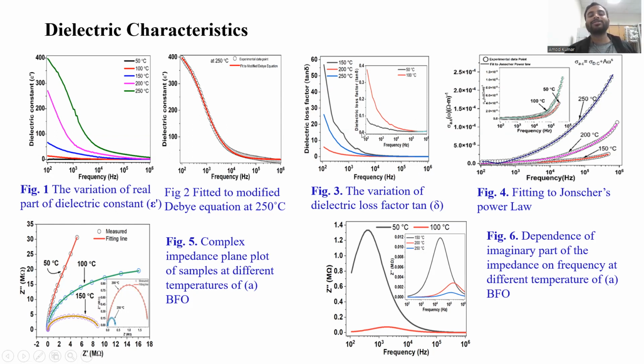So there is the dielectric loss factor. As in the previous one, with increasing temperature the dielectric loss increases, and with frequency the dielectric loss decreases. One important thing is that the development of defect-induced dipoles due to localized electric charge carrier hopping is the main cause of dielectric loss. And this is figure 4.